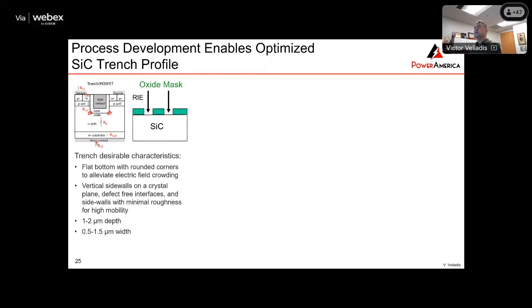The etch of the silicon carbide is to create the trench, so you can have the trench MOSFET. You can make the gate of the trench MOSFET. So as I mentioned before, you use an oxide mask, and after you define the oxide mask, you come with the RIE and etch down the silicon carbide. And some of the desirable characteristics: you want a flat bottom with rounded corners to reduce the electric field crowding at the corner. And you want vertical sidewalls of good quality. You want to minimize the roughness. Depth is anywhere between 1 to 2 microns. The width is 0.5 to 1.5 microns.